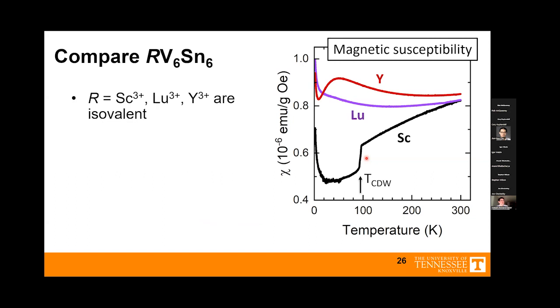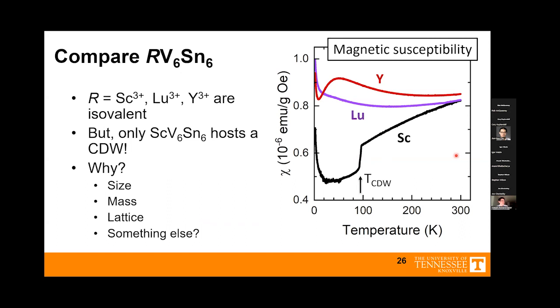But when we do magnetization, we see that of the three of them, a charge density wave only appears in the scandium compound. So why is that? Well, we actually have a really nice situation here. We can independently address whether it's the size, mass, or the lattice that's really making the difference. If you look at scandium, lutetium, and yttrium in size, the order goes scandium, lutetium, yttrium, getting bigger. And in mass, it goes scandium, yttrium, lutetium. That means that we can independently see which one matters more, and we can monitor our lattice parameters to see what matters.